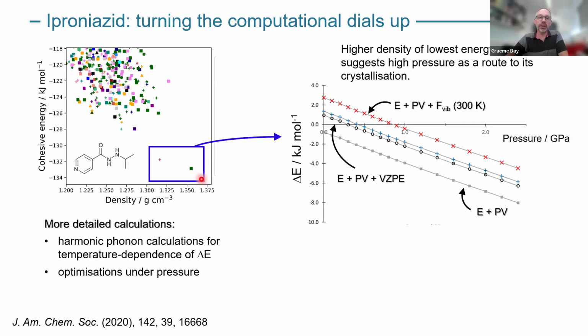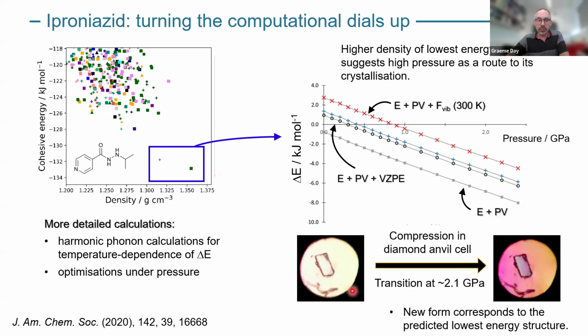Okay, so if we really want to get to this, then this is telling us maybe we should be doing crystallization at high pressure. This is where the Newcastle group came in. They took this crystal structure, they put it into a diamond anvil cell. They put it at, turned out you needed more than 1 gigapascal. You got up to 2 gigapascals, and then you see a transition. And it transforms to this structure here, which corresponds to the unobserved structure. So here the calculations have led us to finding the experimental conditions that you need to make a previously unobserved polymorph. But now we have pretty high confidence that the main polymorphs of this molecule have been found. And that's the key thing that we wanted out of structure prediction.